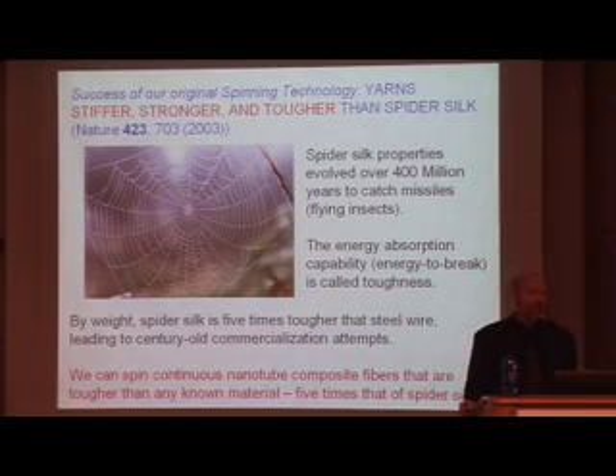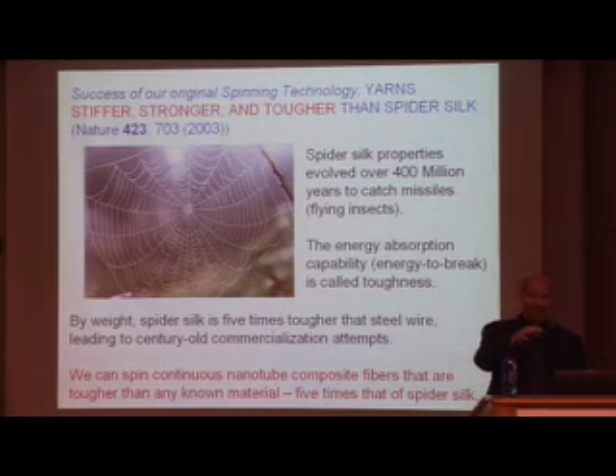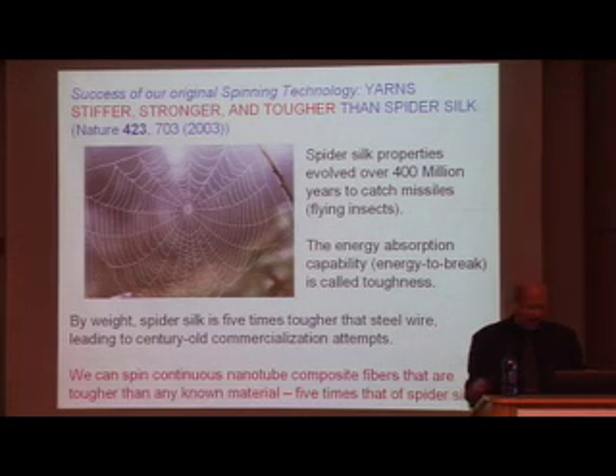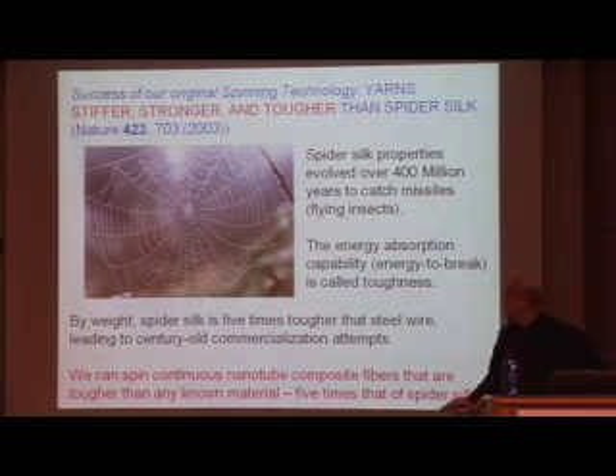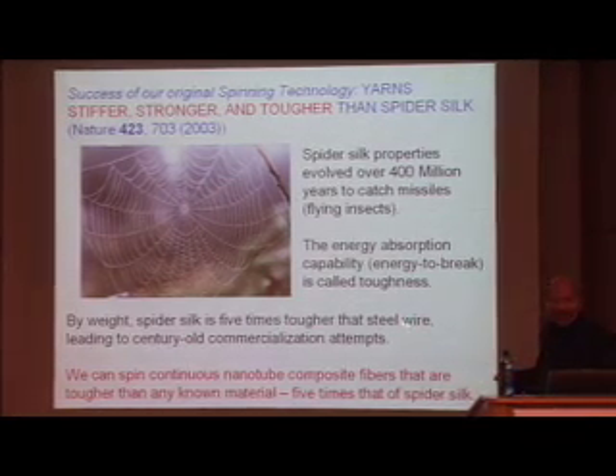It has a toughness of about 150 joules per gram, joule being a unit of energy, gram, of course, weight. We've made carbon nanotube yarns that have a toughness of about 600 joules per gram. Of course, spider silk is about 5 times tougher than steel wire, and the carbon nanotube yarns are about 5 times tougher than spider silk. And how do we make these yarns?